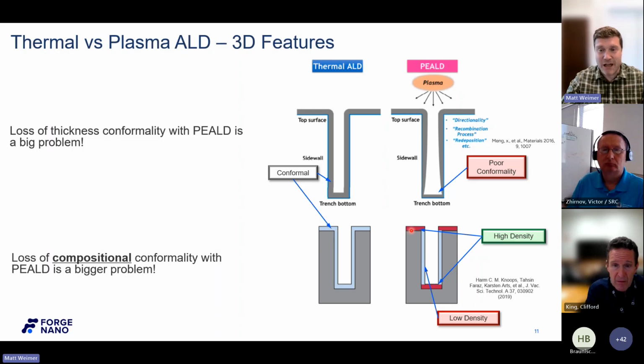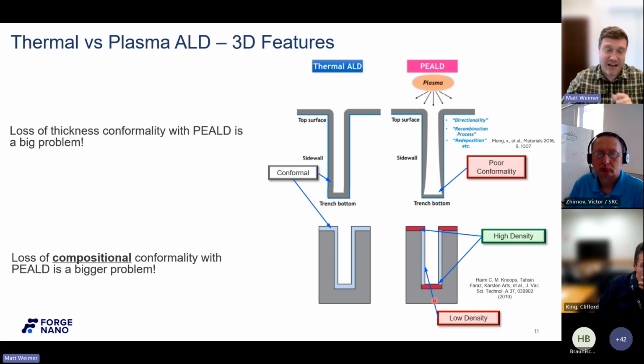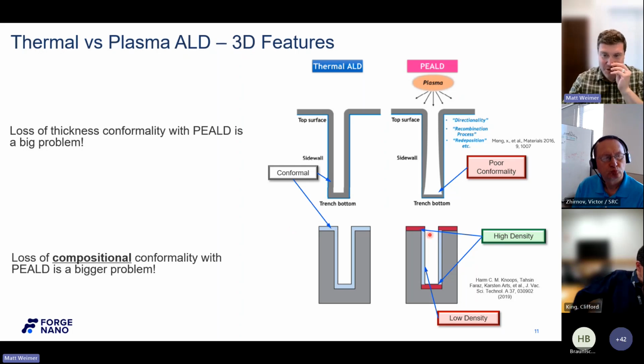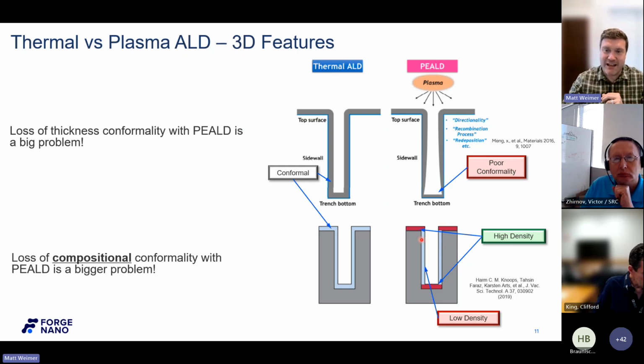So one of the things that people have shown is if you use ions in plasma enhanced ALD to densify the horizontal aspects, you can do what they call topographical ALD, where this sidewall is really low density because it's not getting densified by those ions, and then you can etch it away. Now that's great if you want that. But if you want an ALD process that looks like this, you're not going to get it. So, again, here's what I was speaking to earlier, where the density is different on different parts of the feature.